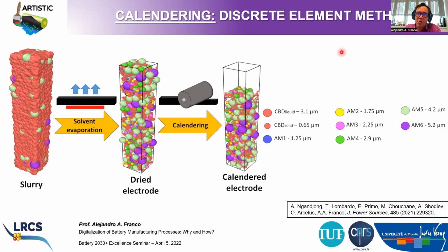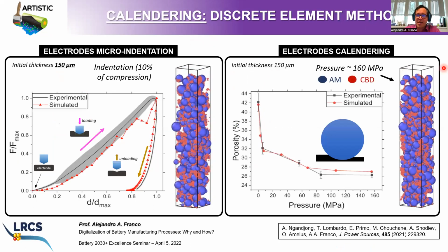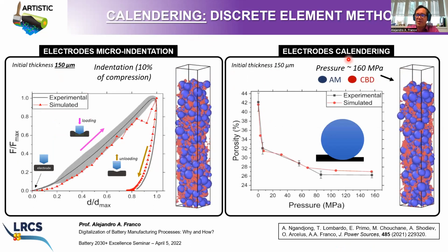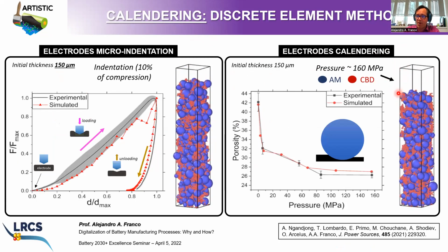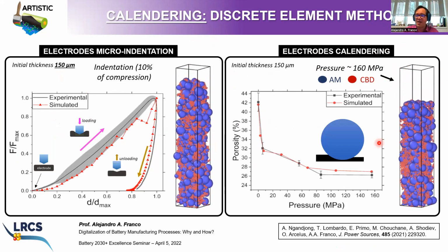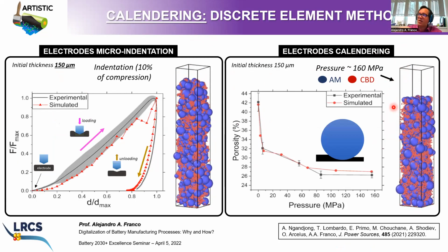This discrete element method model is able to predict the impact, for example, of pressure, okay, or degree of compression on the microstructure of the electrode, right? And here you see an example of simulation. So this is for one applied pressure. You see that the model is able to predict how compression compresses the electrode, right? The thickness decreases. Then you have a plastic behavior there. But also you see that at the end of the compression, the electrode recovers a little bit of the initial thickness, right? So there is a recovery effect. And this is also observed experimentally, right? That means that the model is able to capture both plastic and elastic behavior of the electrodes upon calendering, right?